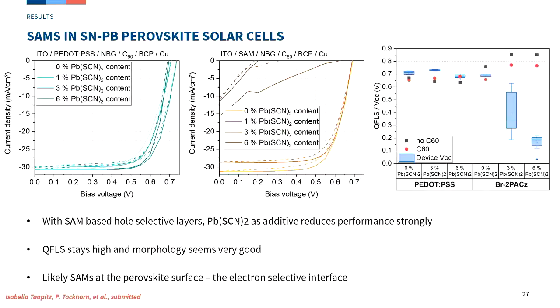Then you can measure the PL, to see how good an LED your solar cell is. If you do that with the additive, the value is very high—here's the SAM contact with the additive, the value is very high.